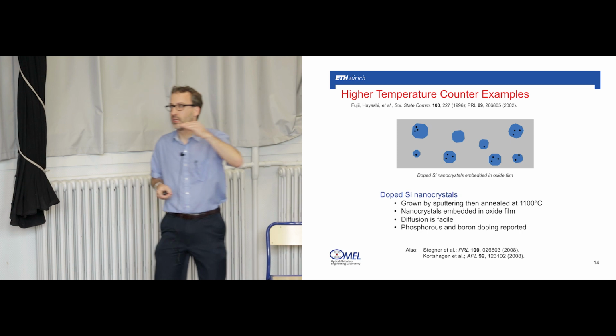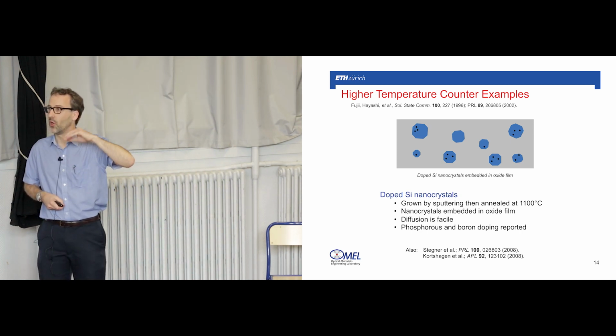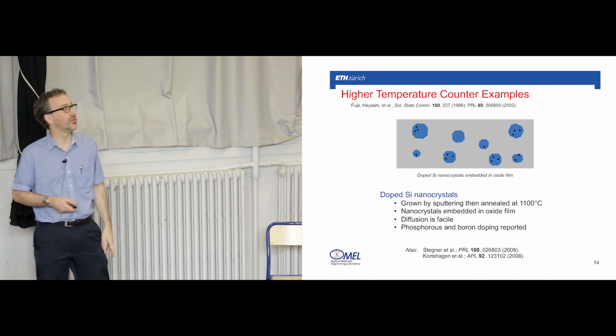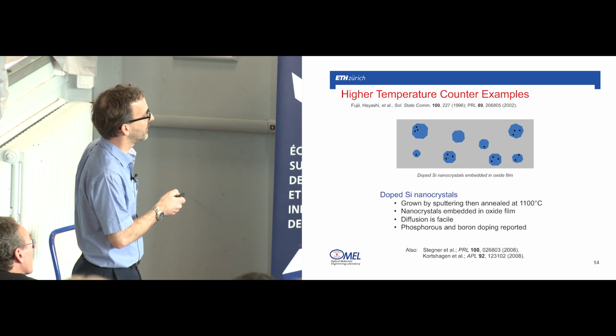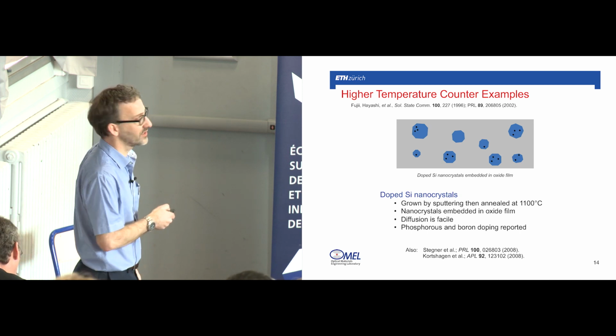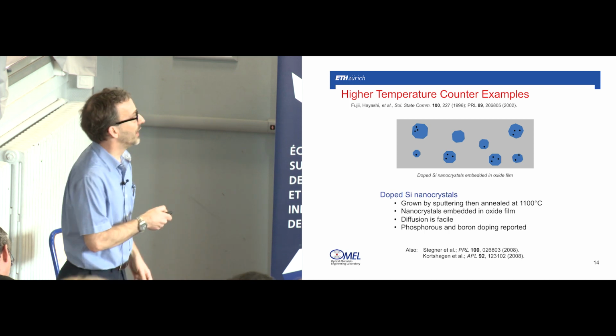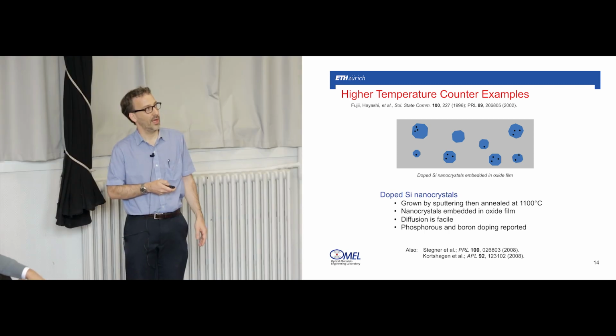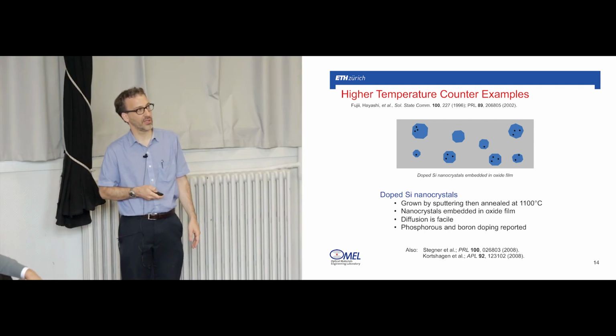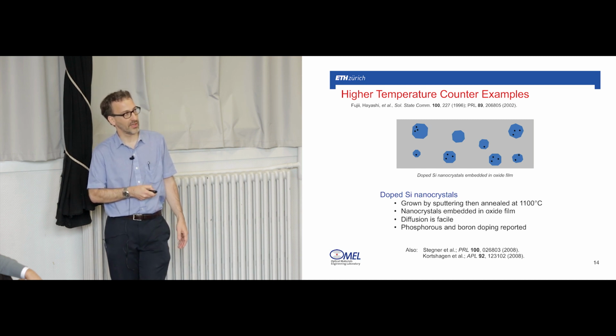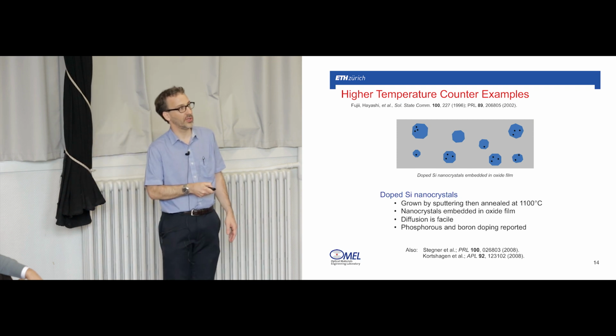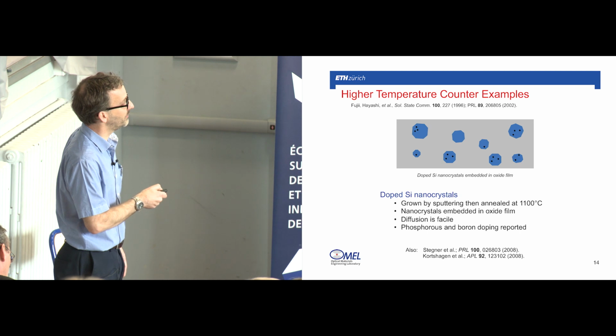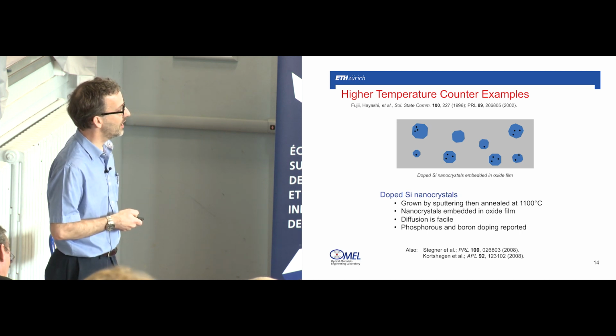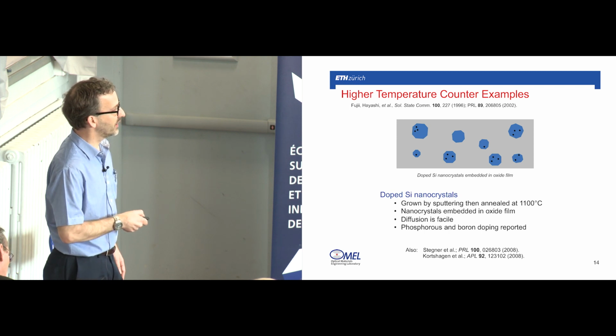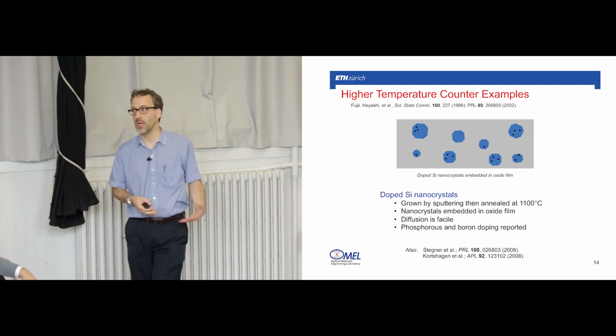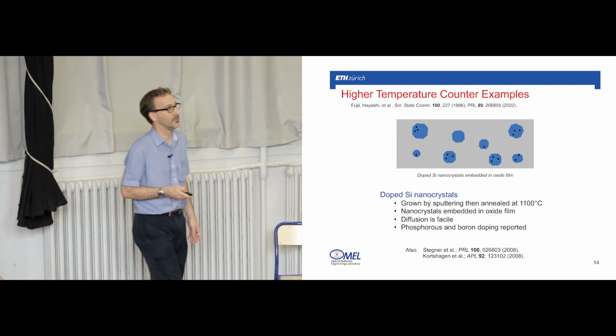Now, if you didn't like that example because it's at low temperature, maybe self-purification really is going on when diffusion is in control, in high temperature growth. There are other counterexamples that rule out self-purification. The Fujii group at Kobe University has done a lot of work since '96 on growing silicon nanocrystals inside an oxide film. These are grown by sputtering and then annealing at very high temperatures, 1100 C. And the diffusion is obviously very fast in these samples. And they showed that you could get both phosphorus and boron doping. They've done maybe 20, 25 papers since this '96 paper on all the properties of these doped particles. And it's also been confirmed in gas phase grown silicon nanocrystals more recently, like in plasma and other methods, that they could dope with phosphorus and boron.